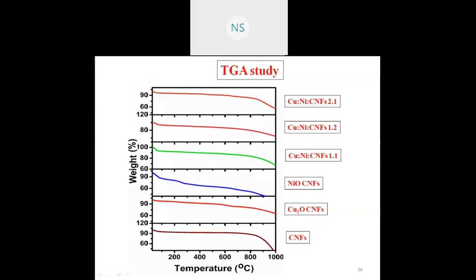So if you look into the thermal stability, all materials are showing very high thermal stability. But the 1:1, 1:2, 2:1 ratios are highly thermally stable as compared to the nickel oxide carbon nanofiber, copper oxide carbon nanofiber, and simple carbon nanofiber.